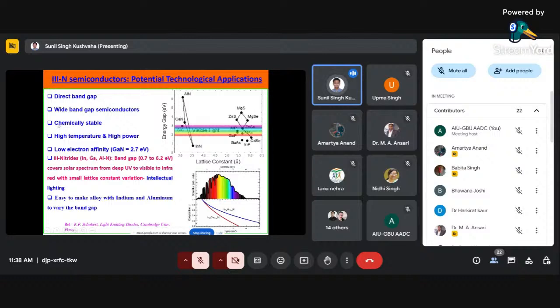When we see especially the energy band gap and lattice constant, we can clearly see different materials have different lattice mismatches. Basically, strain and stress can happen when we are growing a film on different substrates or different layers. But when we are growing the group III nitride materials, there is very low change in the lattice parameter, maybe 3.2 to 3.5 angstrom. So there is minimum lattice mismatch. But you can see the band gap change is huge. You can tune the band gap from 0.7 electron volt to 6.2 electron volt, and gallium nitride is 3.4 electron volt. So one advantage is that you can change the composition of indium nitride, aluminum nitride, indium gallium nitride, and then choose whatever light you want to use in the solar spectrum.